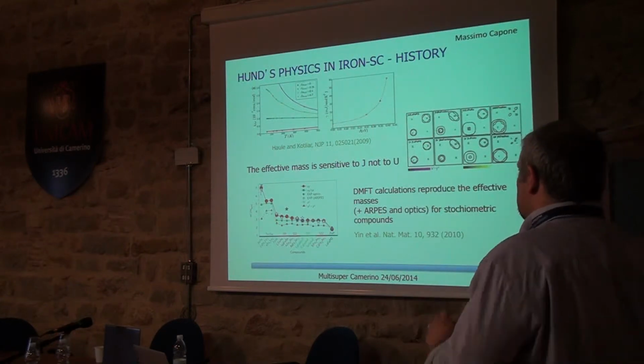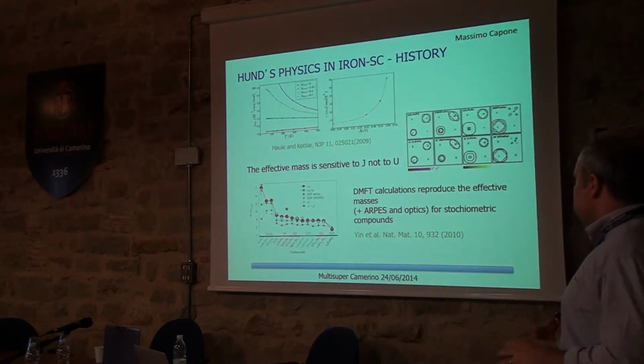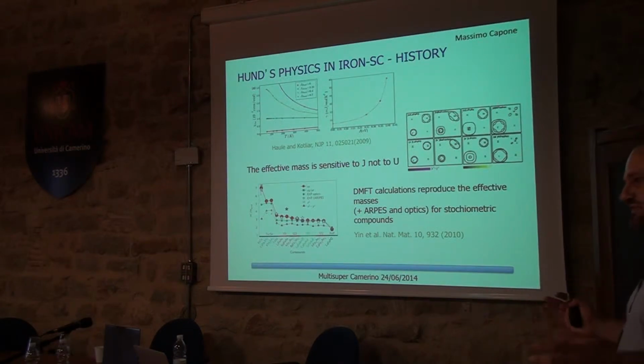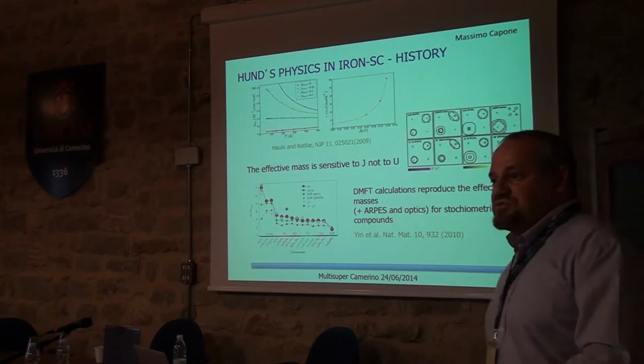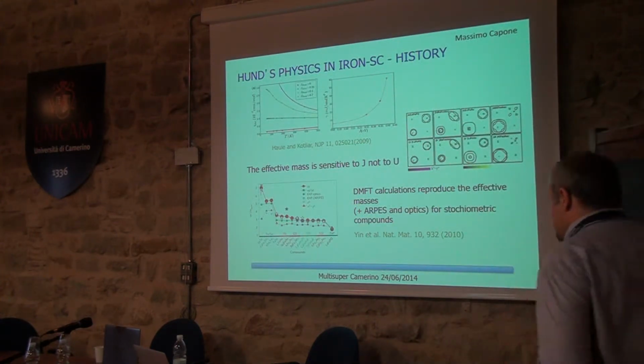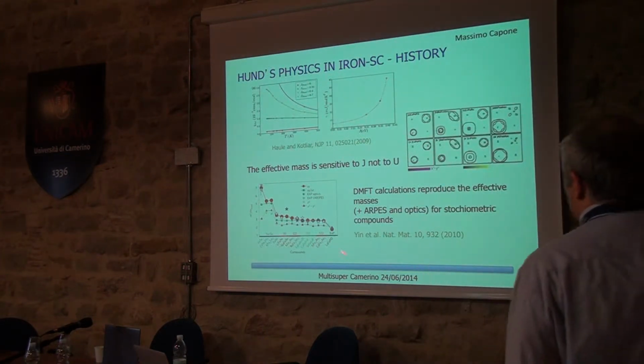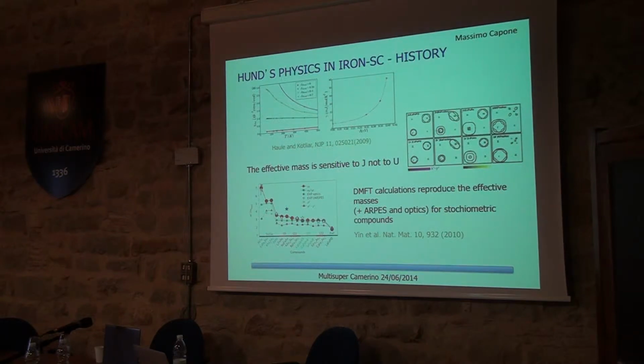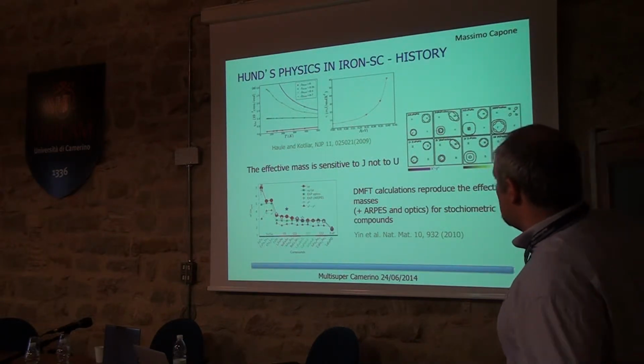Now I will describe the work which uses theoretical methods like dynamical mean field theory as sort of black boxes. You put all the interactions in and you see what happens. Then I will do some reverse engineering, trying to extract what is the physics behind it, hoping also partially to answer what Lara was asking during the previous talks. What turns out is that if you do a microscopic calculation with all the details of the band structure, including the Hubbard U and the Hund's J, you notice that the level of correlation of this solution depends a lot on the value of the Hund's coupling J.